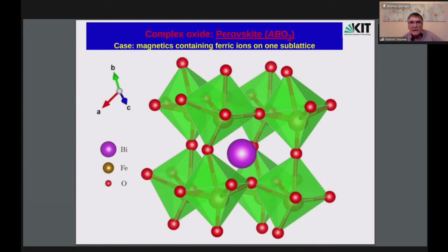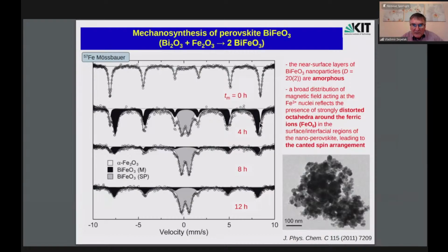you see the progress of mechanosynthesis of bismuth ferrite here, followed by Mössbauer spectroscopy. After 12 hours of high energy ball milling, we obtain a Mössbauer spectrum corresponding to bismuth ferrite nanoparticles in the superparamagnetic state, and this black subspectrum corresponds to the same material in the magnetically ordered state. The system is nanocrystalline with an average particle size of 20 nanometers, and the surface or near surface of these nanoparticles is amorphous. As I showed you at the beginning of my presentation, the surface is very reactive and reacts to electron irradiation.